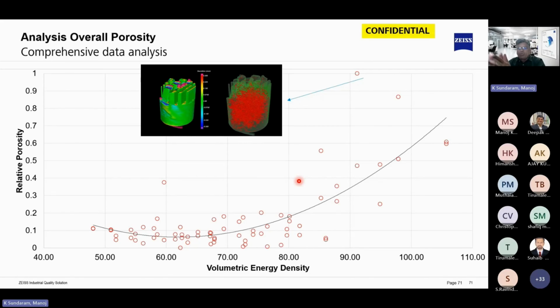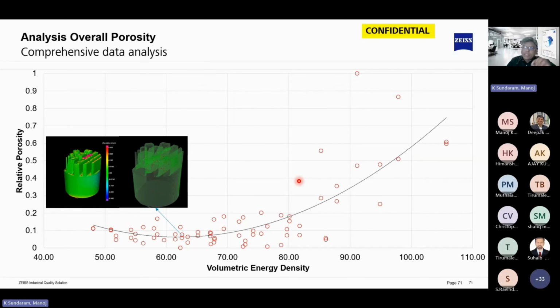So we are then able to give you a visual topic that the part which was worked with a volumetric density of 90 and with certain other parameters is having a very, very high porosity content. Probably you printed it very quick, but the material is not fused properly. Whereas a certain set of artifacts is having a wonderful porosity content, green all over with respect to dimensions. So then you know that when you want to print some critical areas, you would like to use this set